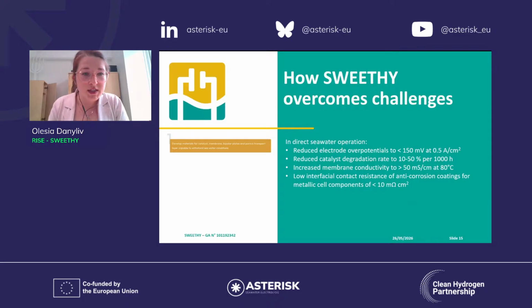The first one is that we will develop the materials and components in the SWEETHY prototype that will be able to withstand seawater conditions. And of course, when we have the objective, we define the key performance indicators for our project. They are defined here, as you see in the slide: for direct seawater operation, we are working towards electrodes with reduced overpotential, catalysts with as low as possible degradation rate, an anion exchange membrane that has high conductivity, and metallic cell components that have low interfacial contact resistance.